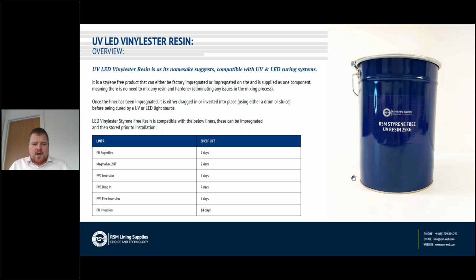Styrene-free resin that is cured using LED is very flexible, holds in the host liner incredibly well, gives us great mechanical properties when used in combination with our Magnaflex glass reinforced material, and is suitable for use effectively across the board of any diameter, really up to 300, 375 in the range.